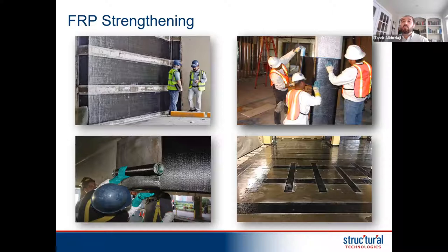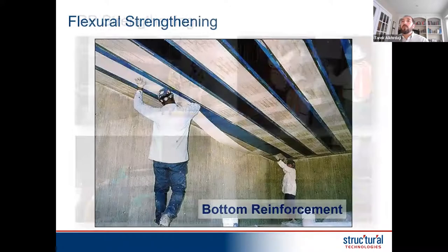It depends on which product you're looking at, but they are much stronger than steel. We're talking about a composite material that is approximately 3 to 4 times and even sometimes 6 times stronger than steel. So you can get very high strength within that simple profile. And because they are thin, they don't change the geometry, they can be easily hidden and therefore don't change a lot the shape of the existing structural elements.